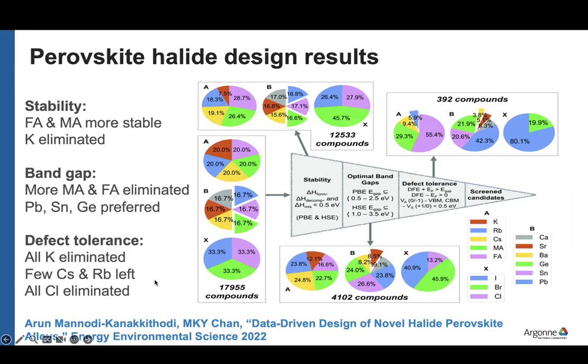So that gives you the reason that the organic A sites were much more successful. By trial and error, people do experiments and they find the ones that perform better are the organics. But what this points to is that it's the defect tolerance that makes the inorganic A sites much worse. So this exercise is dual purpose.